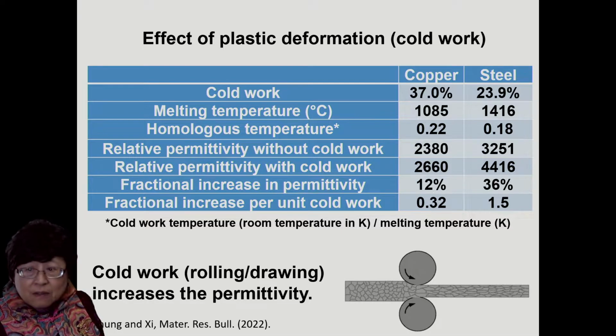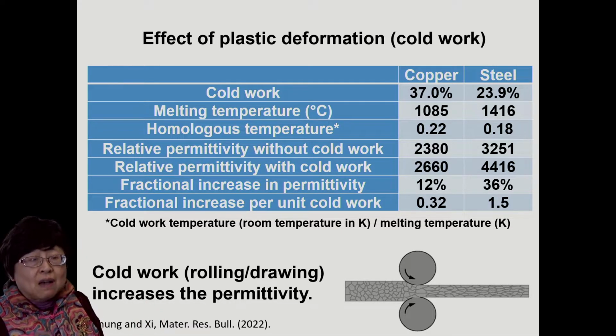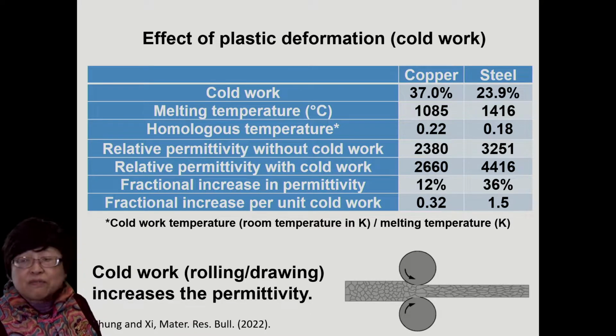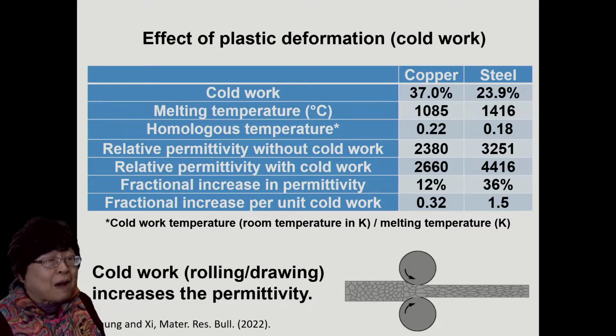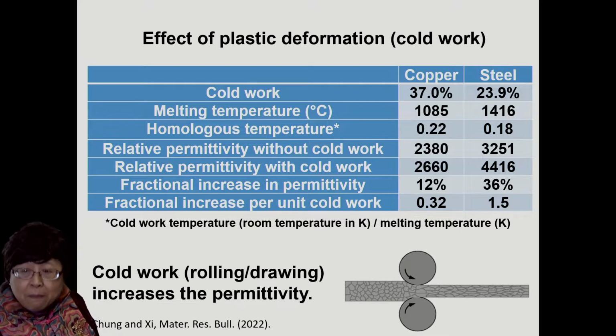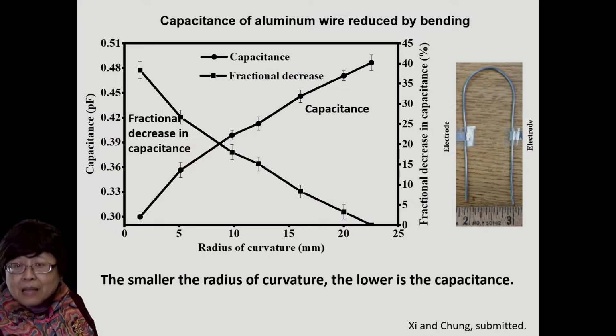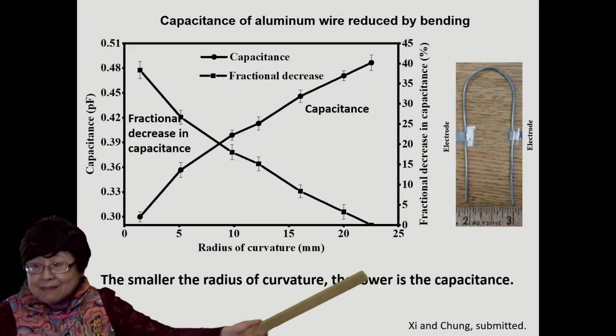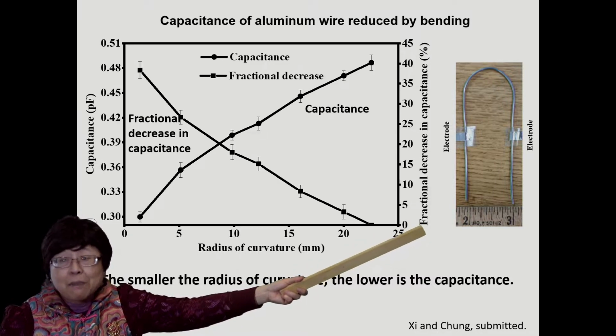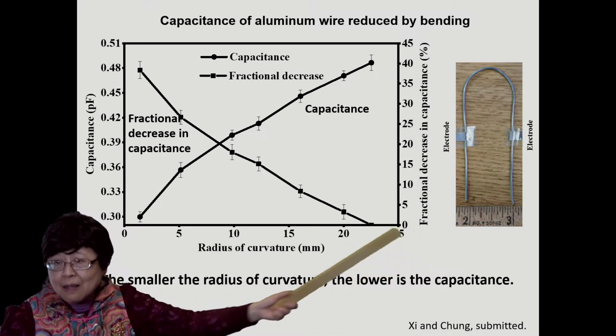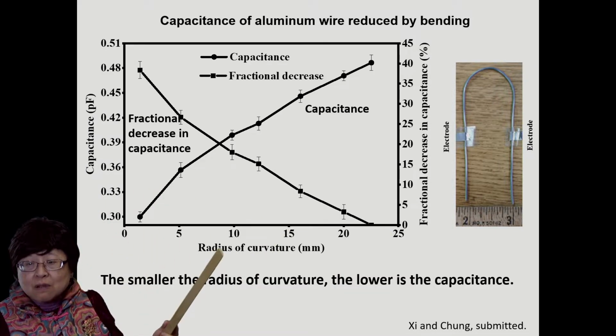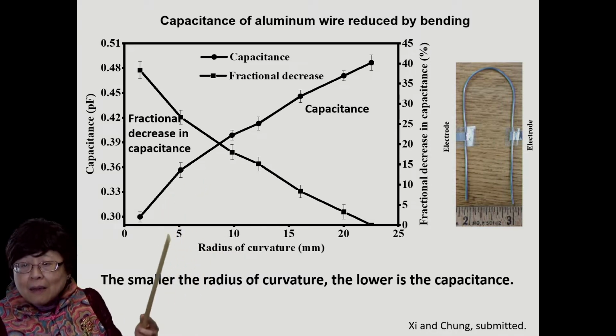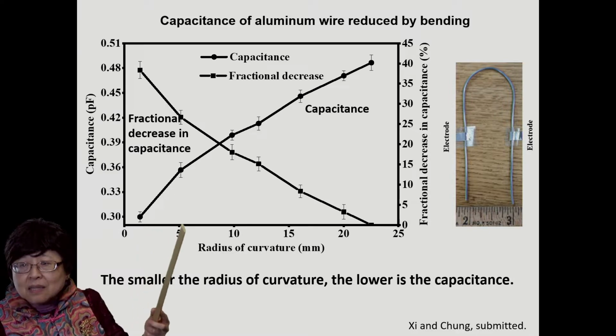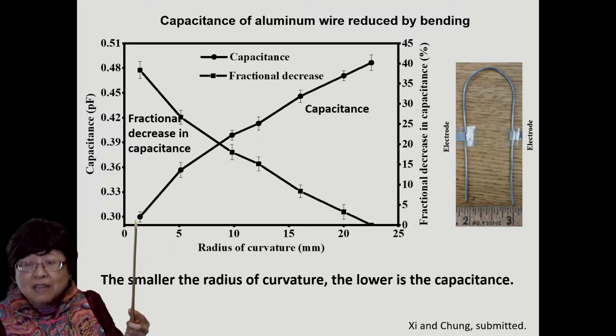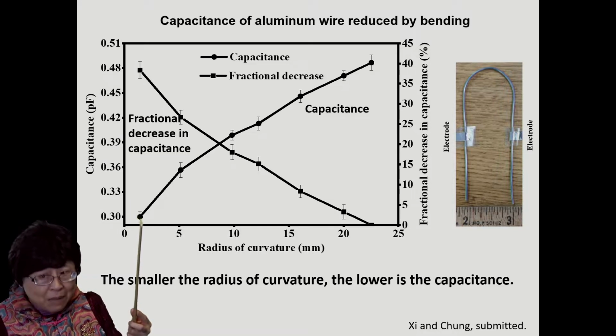So the microstructural effect of plastic deformation, which involves dislocation generation as well as grain size refinement, increases the amount of sites for the electron-atom interaction, thereby increasing the permittivity. Bending affects the capacitance also, but in the opposite direction. This is the capacitance versus the radius of curvature of the bending, and the capacitance decreases as the radius of curvature decreases, meaning the bending decreases the capacitance.